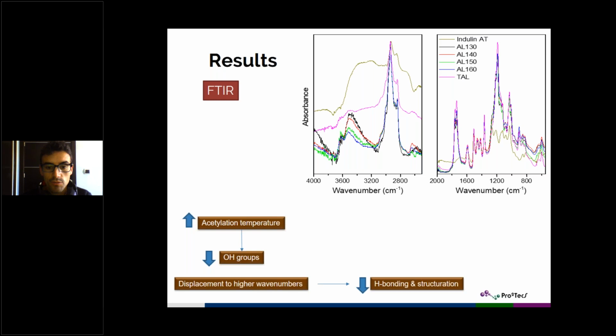That's telling us that we are losing some hydrogen bonding and structuration. So at that point, we can see that the formation of acetyl groups finally makes our acetylated lignin less structured, as a consequence of that acetyl group formation that just dampens the formation of hydrogen bonding.